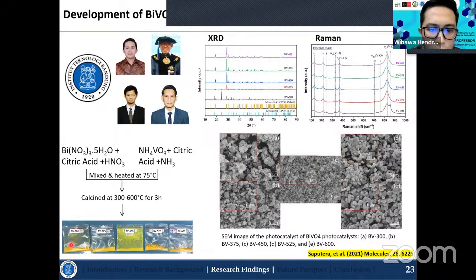And we can see that there is actually a yellowish color generated in here. And we try to characterize the samples. It is actually very interesting, because in here we can see that there are two different crystal structure phases for the bismuth vanadate, including the tetragonal phase and also the monoclinic phase. When it is calcined at 300 and 375 degrees C, it is still mostly in the tetragonal phase, but by increasing the temperature, we can see that the transformation occurred, where the monoclinic phase is also generated.